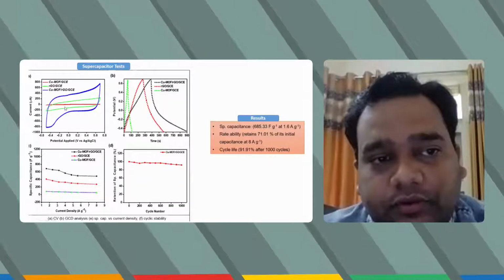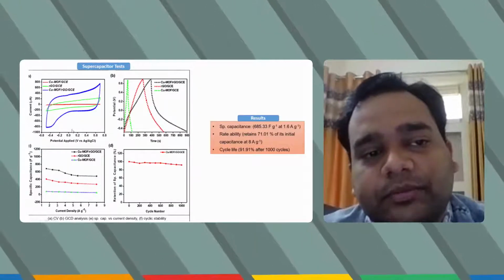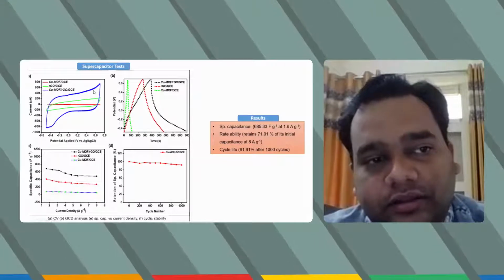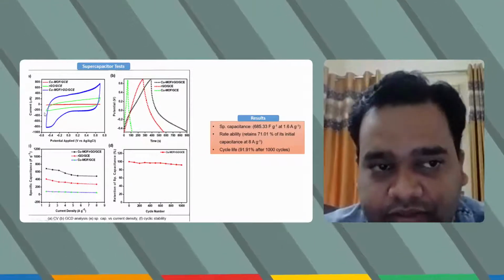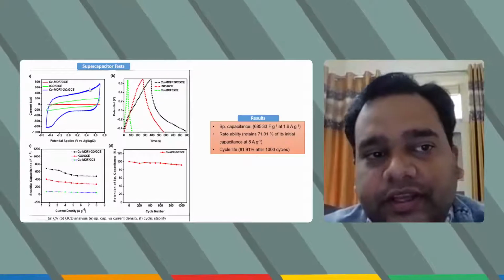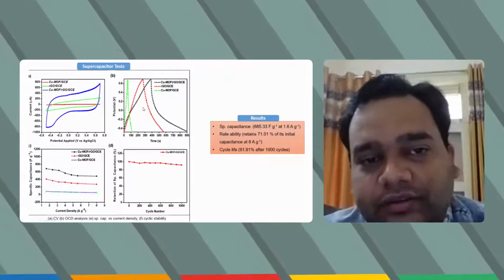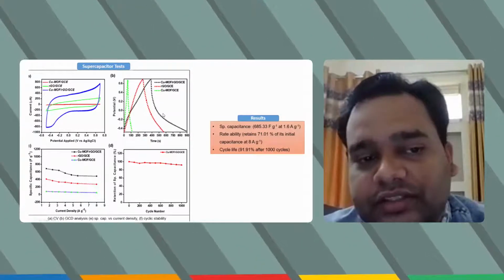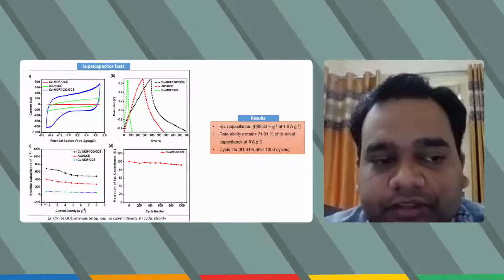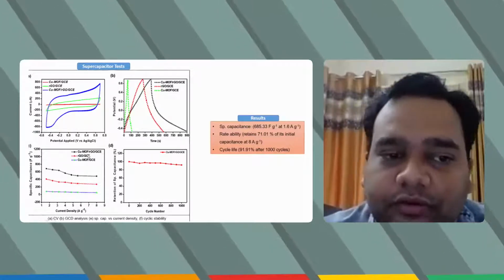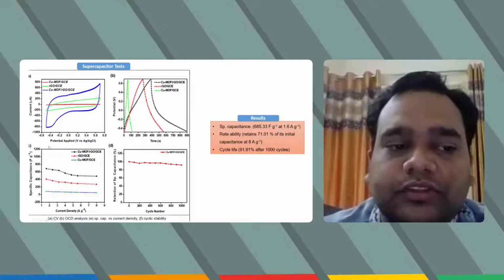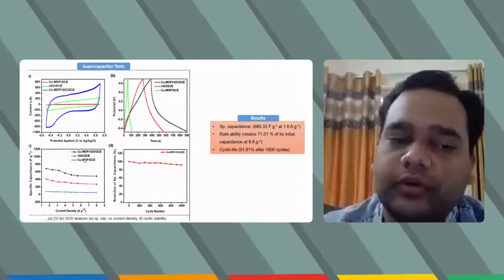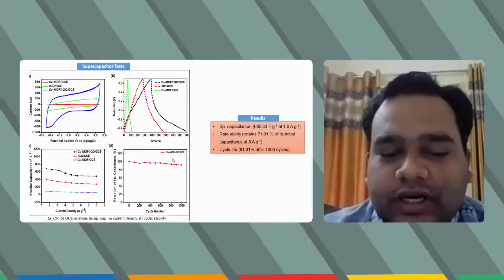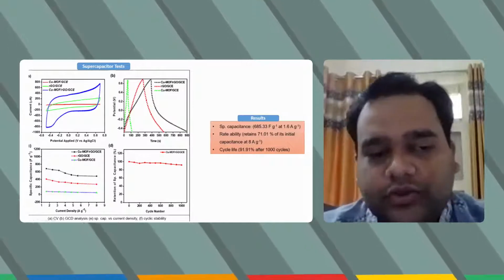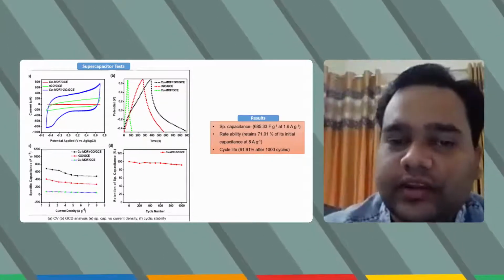We performed this supercapacitor test, and you can see a massive improvement in the charge propagation as well as the integrated area in case of the composite. And similarly, we observe this phenomenon in the charge discharge curve. And when we calculate the specific capacitance, the capacitance of the hybrid electrode was much higher than only copper MOF and only RGO based electrodes. So the motto behind showing these results is that we can make a combination.